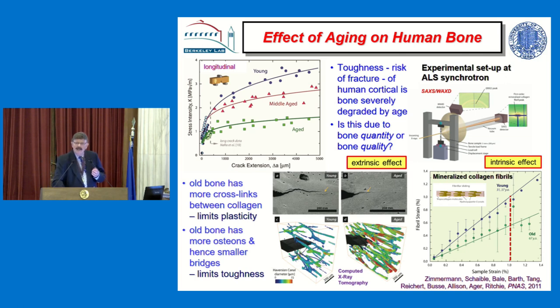Why is that? Well, it's because the collagen locks and it can't pull apart. And it locks because of things called crosslinks. There are a number of different crosslinks, but the ones that are most important are basically due to the accumulation of sugars in parts of your bone, which leads to what are called advanced glycation end products, and they cause the bone basically to be unable to slide. So it's like an embrittlement in a metal, and that's the intrinsic mechanism, because you reduce the ductility, the deformation that the bone can tolerate before fracturing.